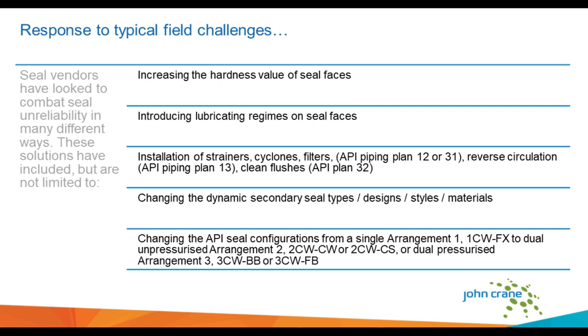Mechanical seal vendors have been aware of the difficulties of sealing crude oil for many years. As line pressures and line hydraulics have increased, these issues have become more pronounced. Various steps have been taken to try and mitigate the resultant reduced seal life and leakage. These steps have included increasing the hardness of the seal interface materials. This helps where poor lubrication is experienced at the interface, but is often not the case, and the dynamic seal faces come out in excellent condition, yet the seal has suffered excessive leakage.